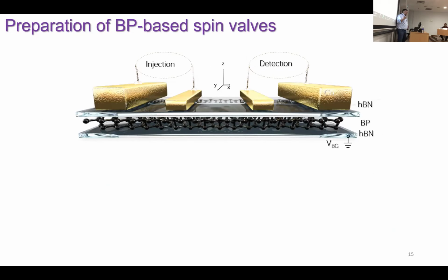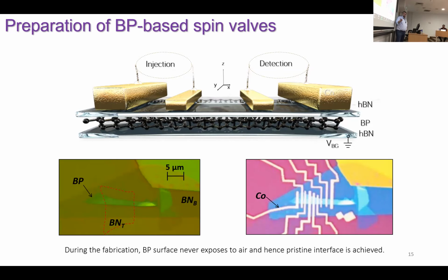Okay, so this is the device structure that we made here. We have again the black phosphorus, and black phosphorus has some disadvantages as well that I didn't say. It degrades very fast, so you need to make all the devices in a glove box environment. Here we are using a very thin layer of hBN, like 3 layers of hBN, as an encapsulation layer and also for better spin injection efficiencies. And we just form the regular cobalt electrodes on top. These are some example device pictures before and after the metallization process. We do all these processes inside the glove box environment, so the surface of the black phosphorus never gets exposed to air or anything else.